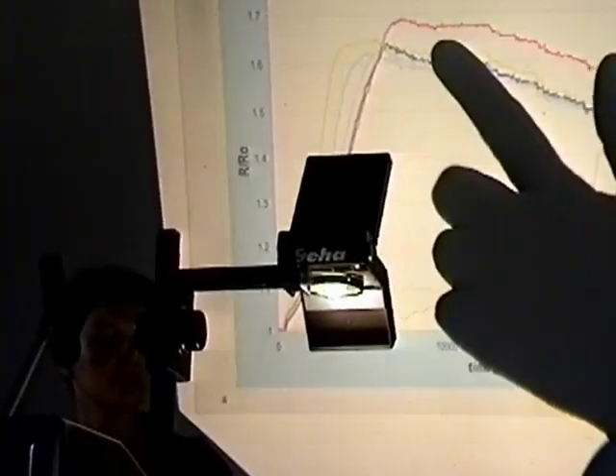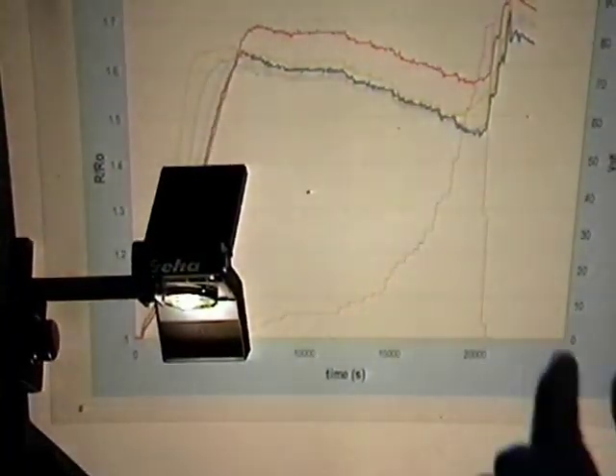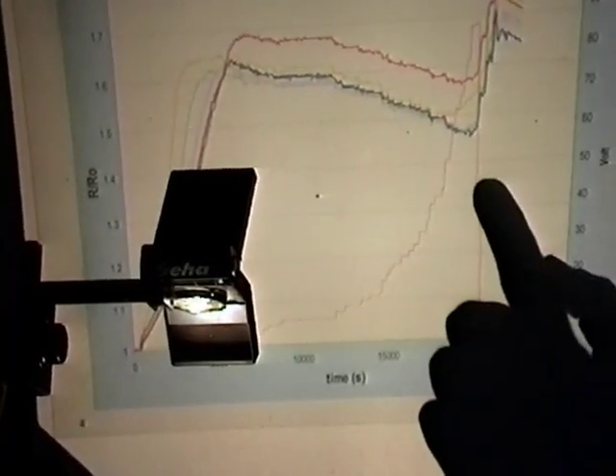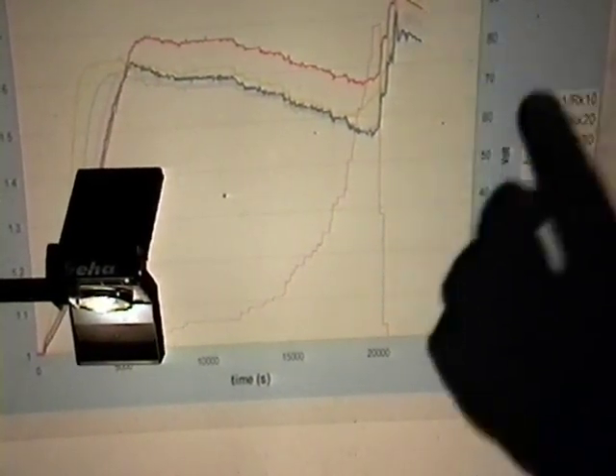We did other experiments using a wire. This is the same electrical configuration, but using a wire, 2 meters long, 50 microns in diameter. In this case, the effect is less than in the previous one, but it's still there. The maximum here is 1.7 instead of 1.8. It's an interesting feature that during deloading, the maximum reaches a higher value. Then the wire usually breaks.